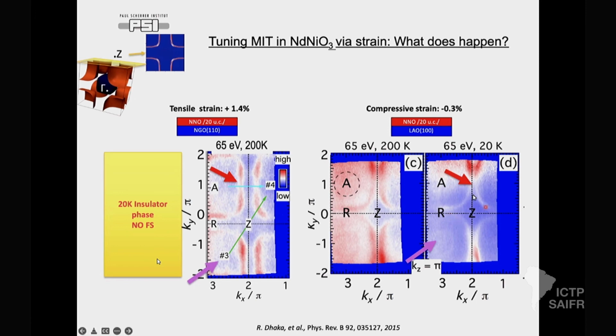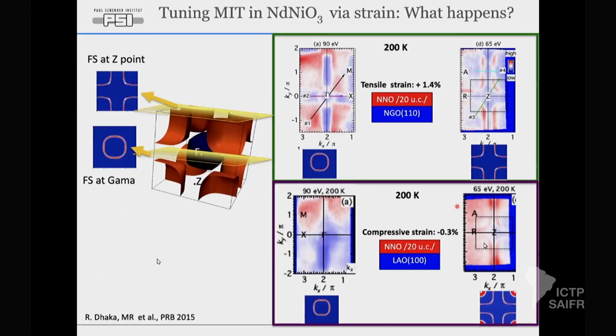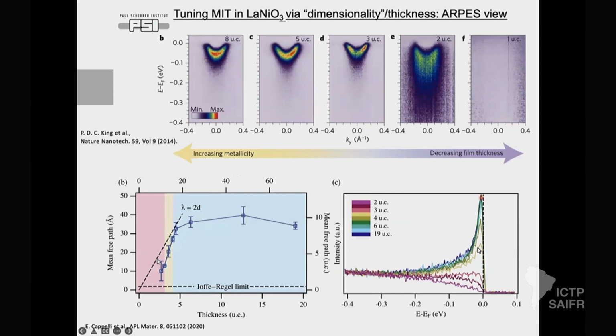We see this by ARPES. So the spectral weight, you could see this is weak spectral weight. The Fermi surface is existing, but compare here, which is a much stronger spectral weight than here. Okay. So the claim from ARPES is that you only see lower spectral weight. Yes. Look at this. That is what happens basically in the metal insulator transition. So the spectral weight goes down, but the Fermi edge is still there. And the mean free path goes down also in some sense. Of course this is lanthanum nickelate, but it's a similar effect with temperature. So the spectral weight is redistributed, the system goes toward insulator behavior because conductivity is much lower, but still not yet an insulator.